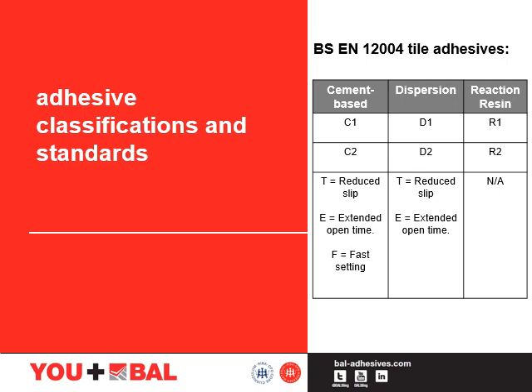Moving on to the classifications, we have 1, which is a normal adhesive, 2, which is an improved adhesive. This meets the requirements for additional characteristics. Then we have a lettered system. So F is a fast setting adhesive, normally cementitious only, and that achieves 0.5 newtons per millimetre squared within 6 hours. T, which is non-slip, that's normally used on walls. And then E, which is an extended open time, which is over 30 minutes. This is for cementitious and dispersion adhesives only.